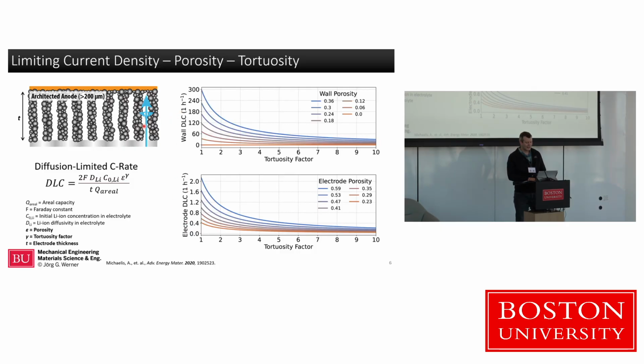Now we also look in our hypothetical architecture here at, well, these walls, let's say they're 10 or 20 microns thick, right? So if we just look at 10 or 20 microns, how does the picture look here? Well, now we're getting to C rates really almost independently of porosity, so 18, 24%, we're getting C rates of 60.